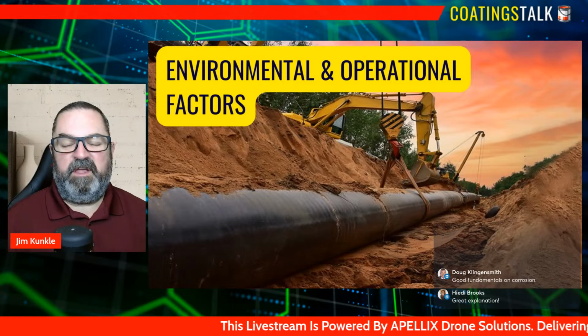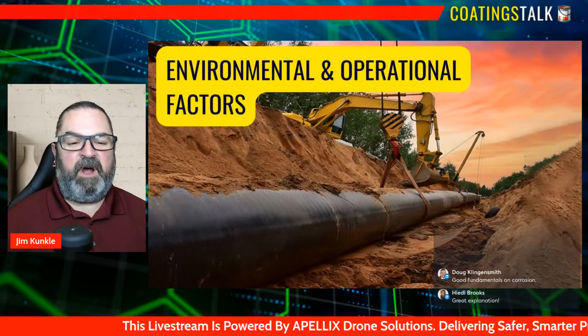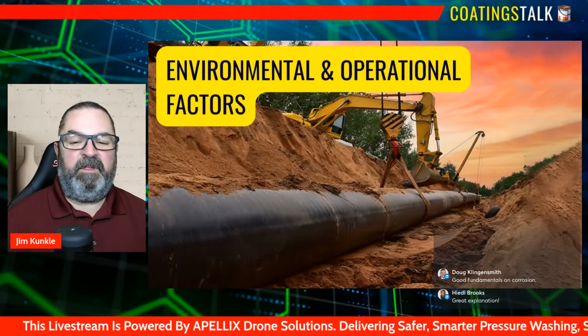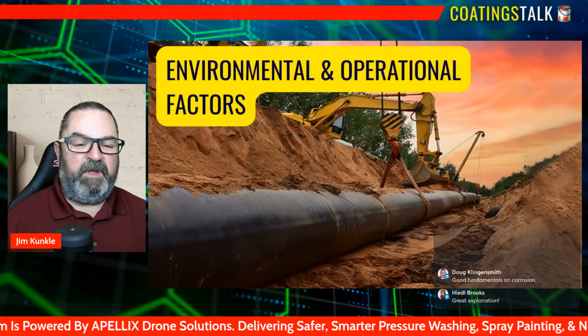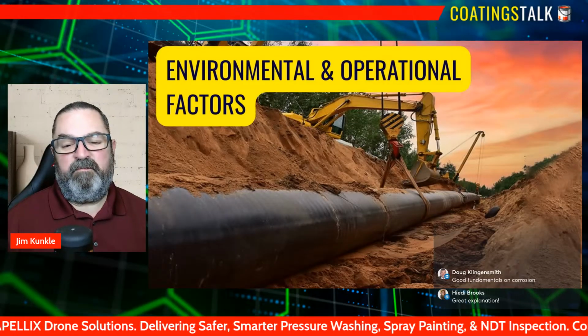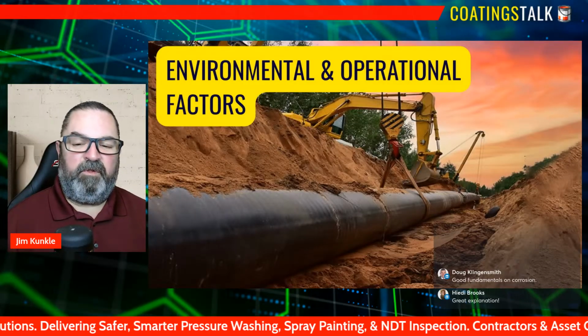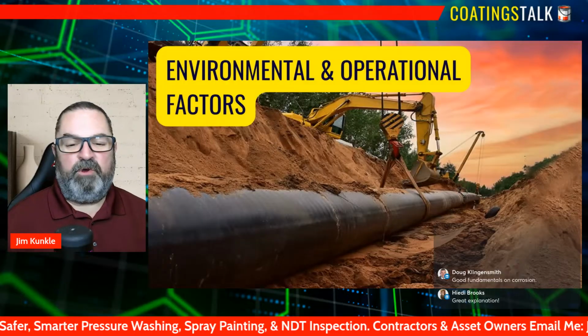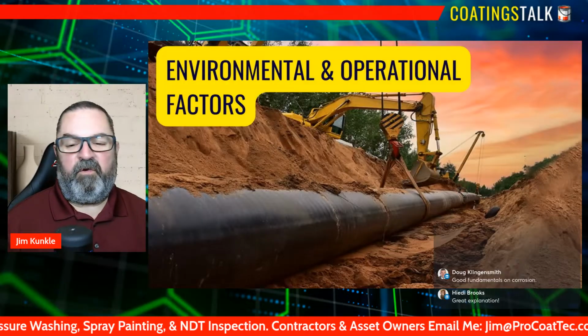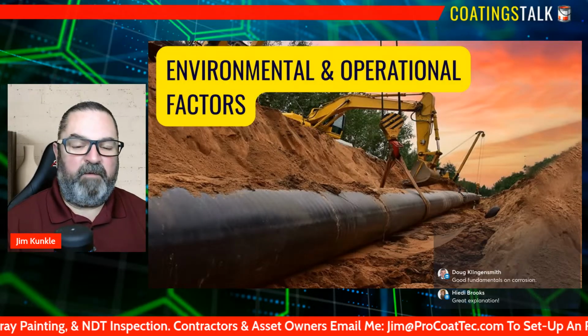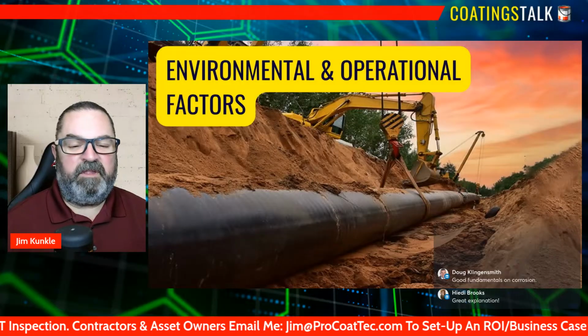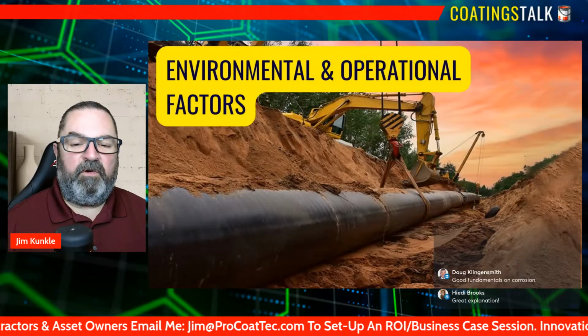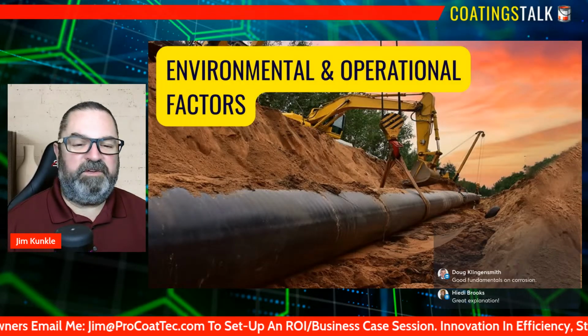In contrast, inland environments, especially dry or low humidity regions, tend to experience slower corrosion rates, but inland doesn't mean immune. Industrial pollutants, temperature swings, and moisture traps can still create highly corrosive microenvironments, especially around equipment that cycles between hot and cold or sits near chemical processing operations.